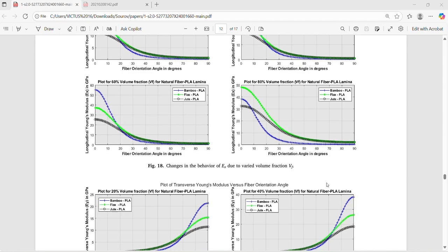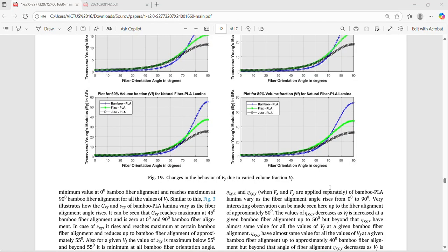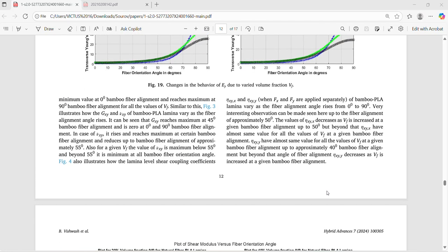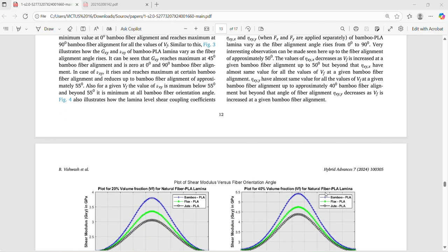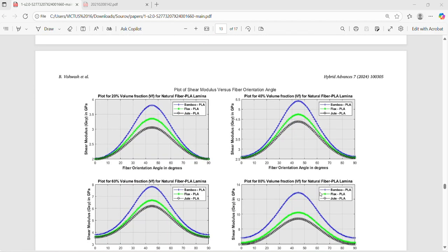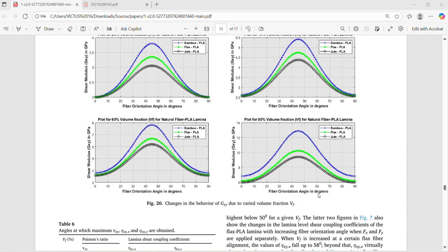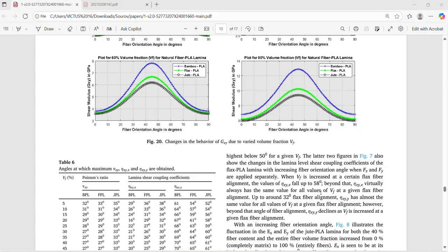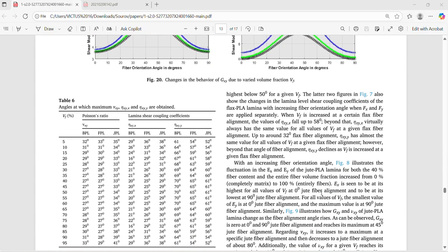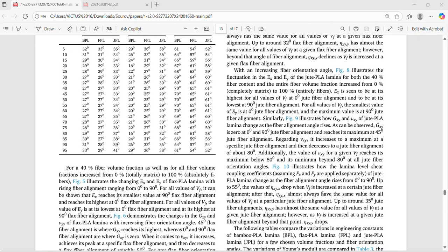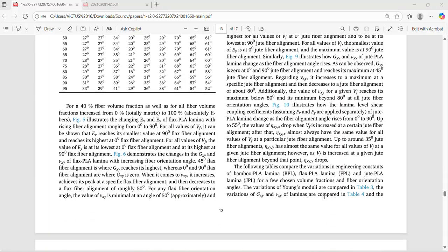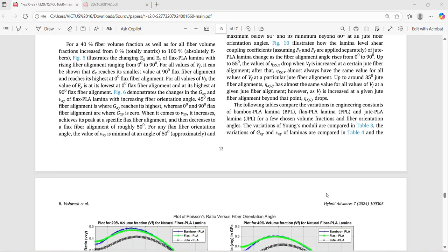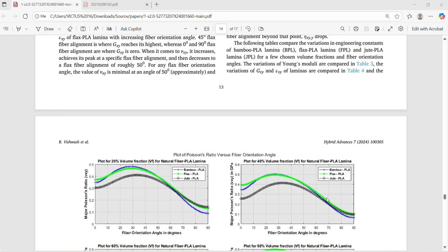Among the three composites, bamboo PLA consistently demonstrates the best mechanical properties, particularly in terms of shear modulus and shear coupling coefficient. Flax PLA shows a higher Poisson ratio and balanced stiffness, while jute PLA, though mechanically weaker, remains valuable for its cost effectiveness and biodegradability. These findings confirm that both fiber type and orientation significantly affect composite performance, with bamboo emerging as the most effective reinforcement material overall.